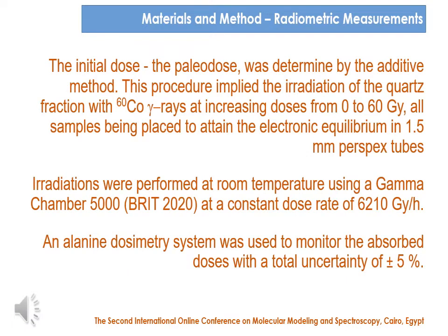The initial dose absorbed by investigating loess layer since its deposition and present time, I mean the paleodose, was determined by the additive method. This procedure implied the irradiation of quartz fraction with cobalt-60 gamma ray at increased dose from 0 to 60 gray, all samples being placed to attain the electronic equilibrium in 1.5 mm perspex tubes. Irradiations were performed at room temperature using a gamma chamber at a constant dose rate of 6,210 gray per hour, monitored by alanine dosimeters with a total uncertainty of about 5%.